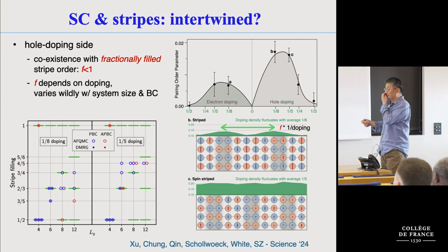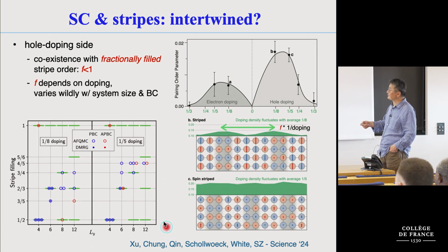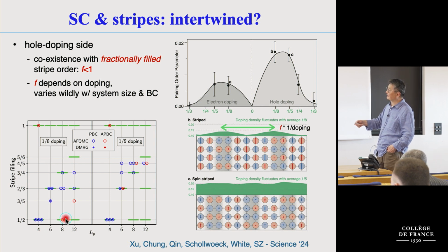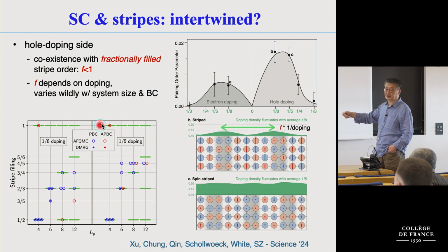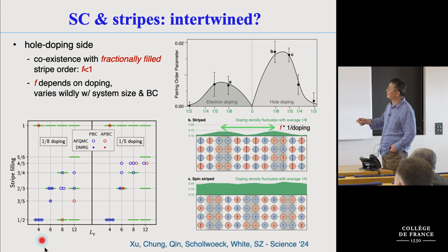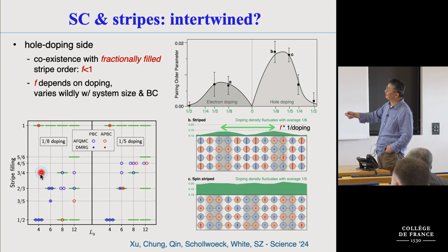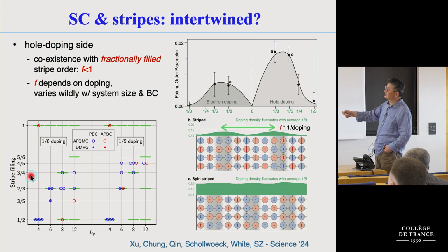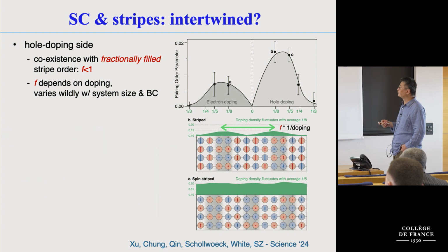We spent a lot of effort trying to do very large systems to figure out what this fraction is. You can see as you go to the right, it's trying to go to the thermodynamic limit, but we were never able to converge it. One thing we see very clearly is that it's not an integer. It's not 1 or 1/2, which is what current predictions have been based on, mostly DMRG, right? But that's because those are very narrow cylinders with periodic boundary conditions. So it's a fraction somewhere between 80% and 75%, something like that.